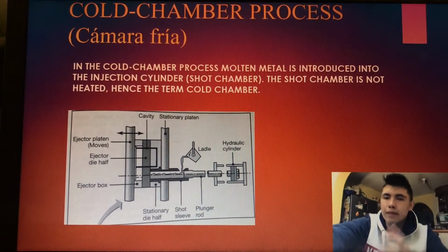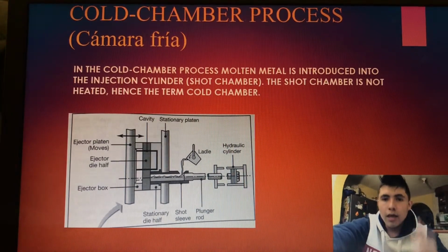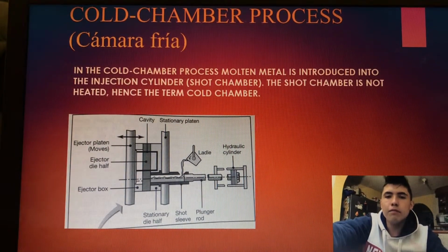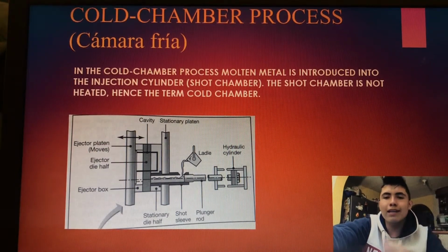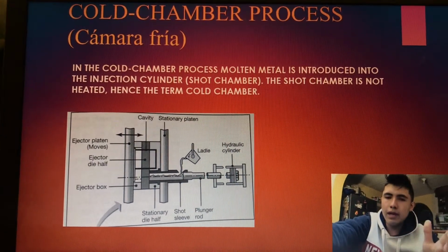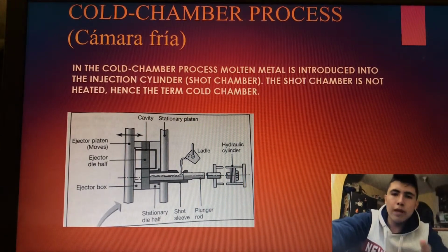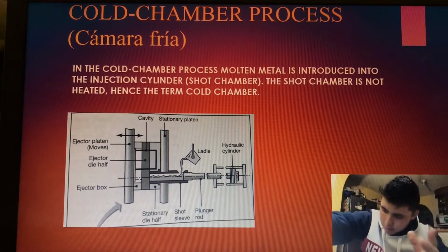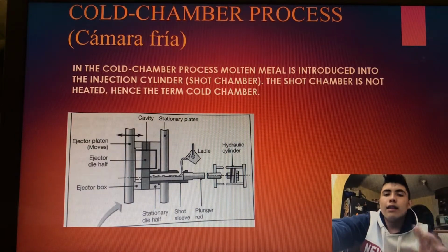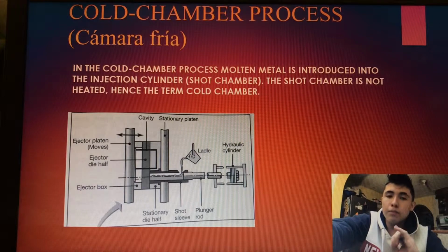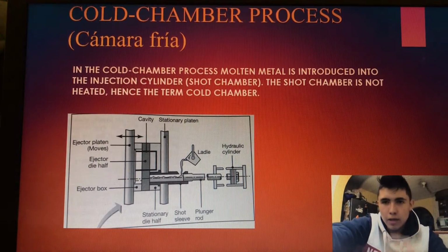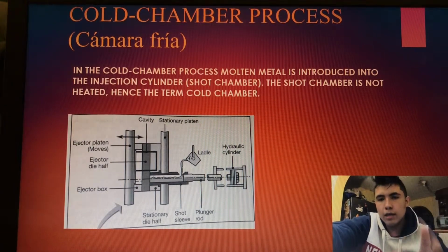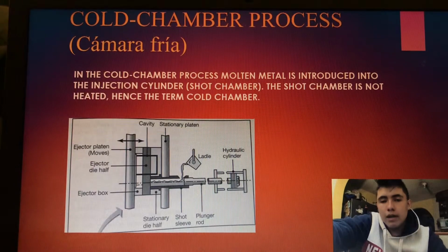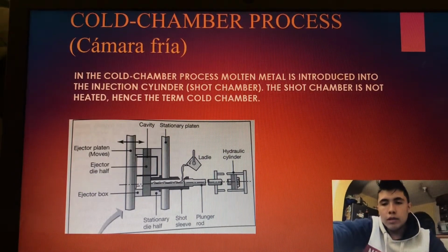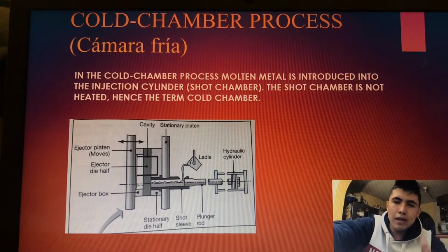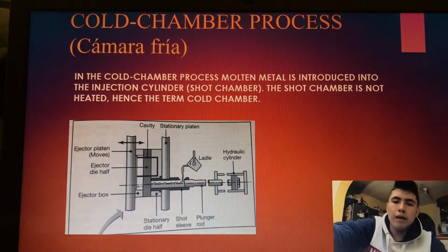In the cold chamber process, molten metal is introduced into the injection cylinder. The shot chamber is not heated, hence the term cold chamber. The metal is forced into the die cavity at pressures typically ranging from 20 to 70 megapascals, although they may be as high as 150 megapascals. The machines may be horizontal or vertical. Aluminum, magnesium, and copper alloys are often cast by this method, although other metals, including ferrous metals, are also cast. Molten metal temperatures start at about 600 degrees centigrade for aluminum and magnesium alloys and increase considerably for copper-based and iron-based alloys.